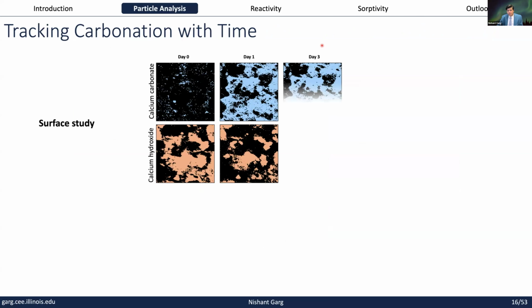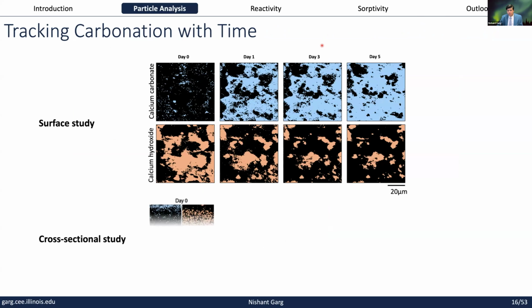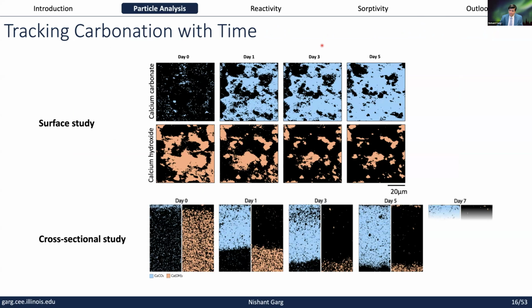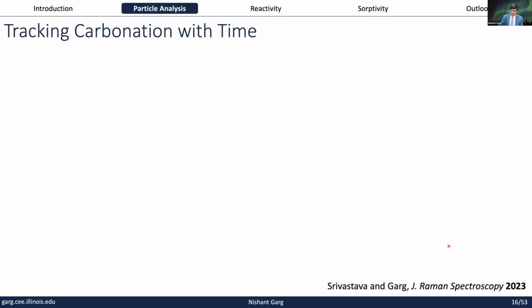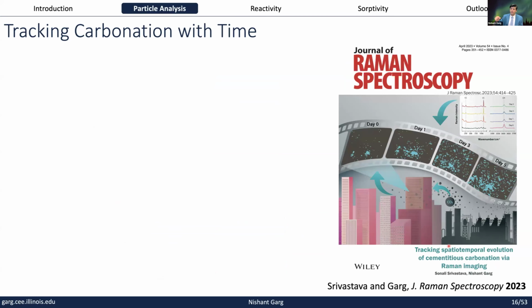Then we have also looked at other things where we track carbonation over time. So we take a sample, we seal it from all the sides, and then we just expose it to CO2 from the top, and we see how the calcium carbonate front is moving inward and the calcium hydroxide front is moving back. And we can see clearly there's a diffusion barrier that forms, which ultimately stops that carbonation because the CO2 cannot get further in. So the idea was to create a movie of carbonation of a sample. And this was the work we did a couple of years ago.